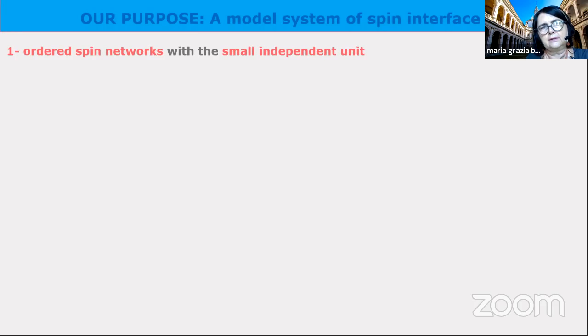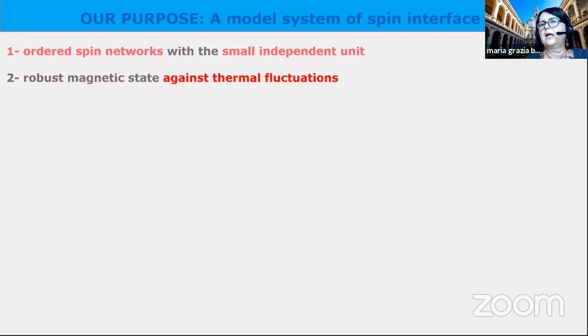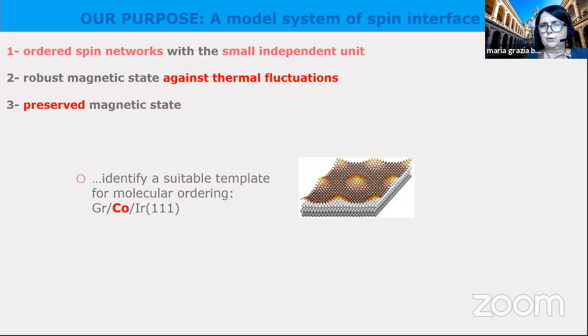So we need ordered spin networks with small independent units. These molecules are for us this iron phthalocyanine with a high magnetic moment. So we organize this on a surface in this way because we have to preserve the magnetic states, and we would like to have a magnetic state that is stable against thermal fluctuation even at room temperature.